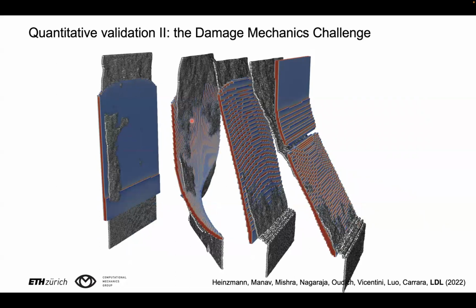So you see that the agreement between computational and experimental surface is very, very good, except for the upper portion of the crack, but only for this case, which is probably to be explained by the fact that in this region there are significant compressive stresses. I'll come to this much later in the talk.